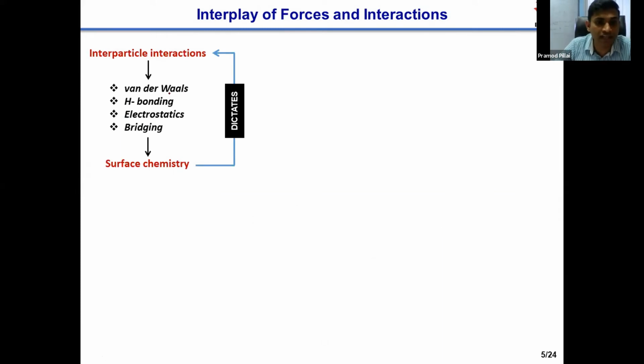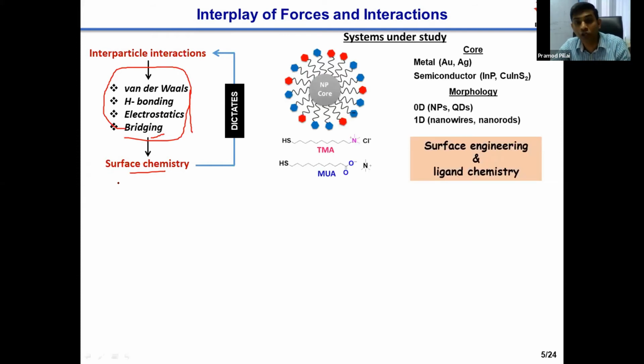These are some of the non-covalent interactions that we are interested in. We work with van der Waals forces, hydrogen bonding, electrostatic and bridging interactions. And as I said in the previous slide, all these non-covalent interactions can be varied by varying the surface chemistry of the nanoparticle. From a chemist's point of view, all these interactions originate from atoms and molecules. So if you can organize the atoms and molecules around a nanoparticle, then you may be able to control these various non-covalent interactions. And this is exactly what we do in our group.